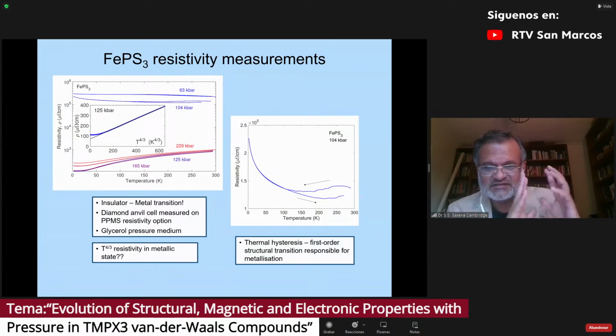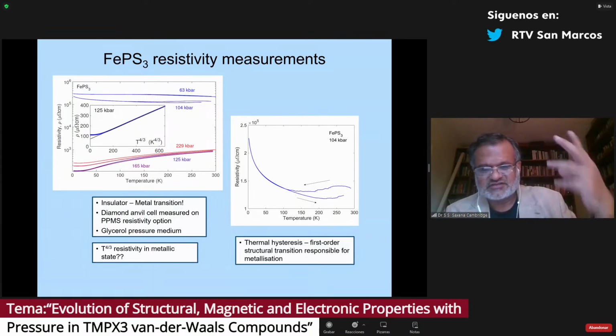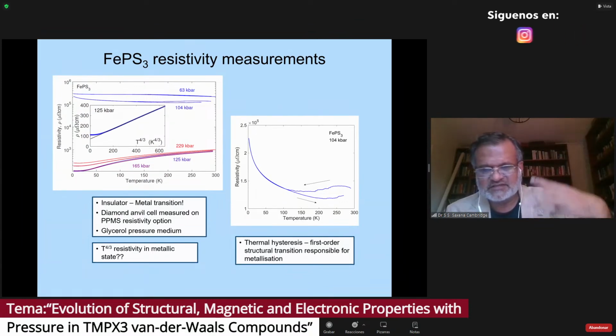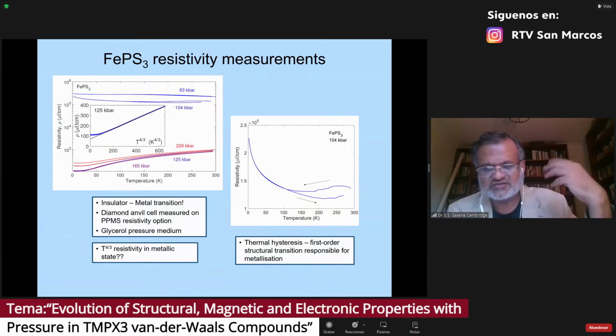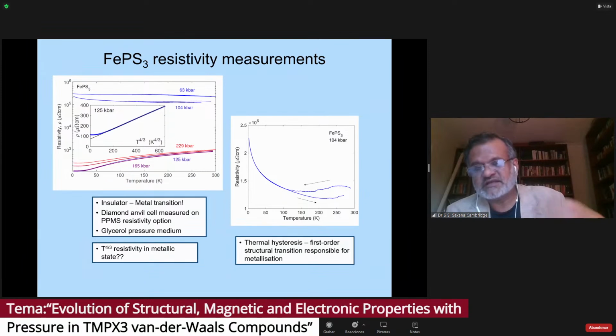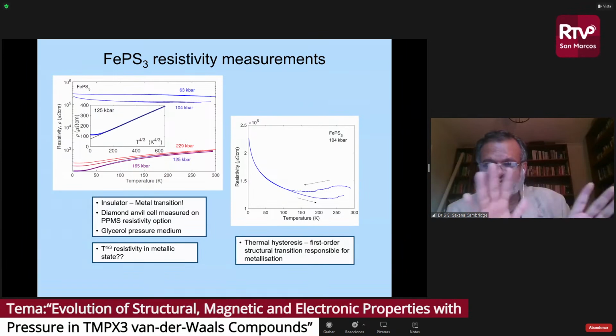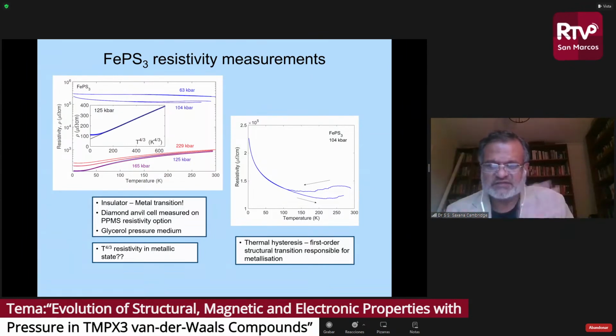So what we think is happening is that the antiferromagnetic system in that material, when we apply pressure, goes through a transition, and the magnetic order becomes unstable as it crosses the boundary, and then we have short-range magnetic order in the system. When the system becomes metallic, it forms the Fermi surface, and those electrons then start to see those fluctuations and scatter off them, creating a very unusual state, very similar to the strange metal type of state, when the system becomes metallic.